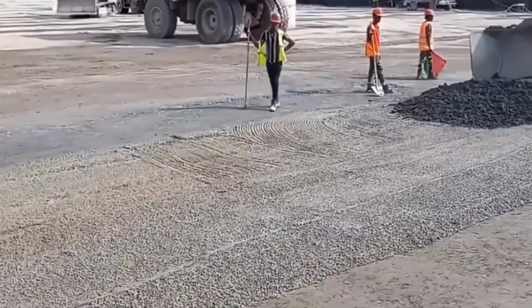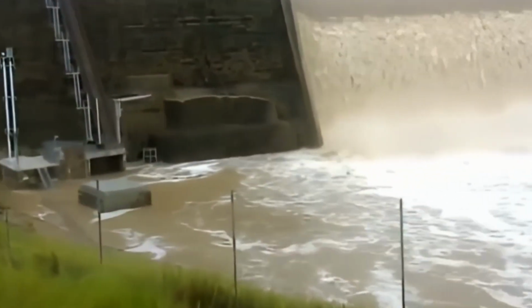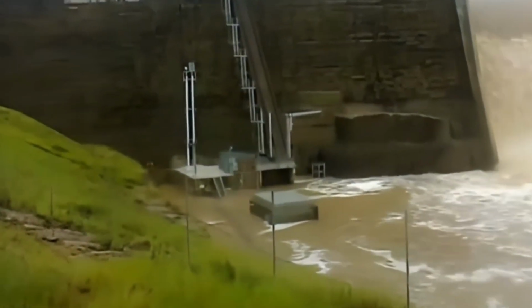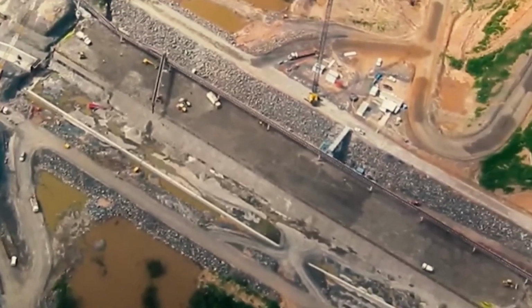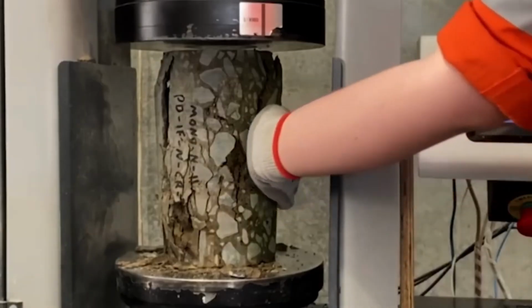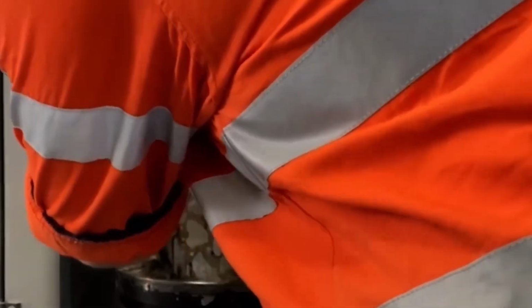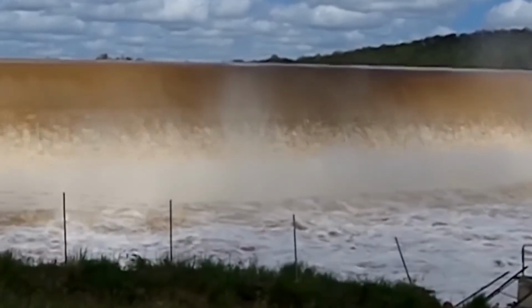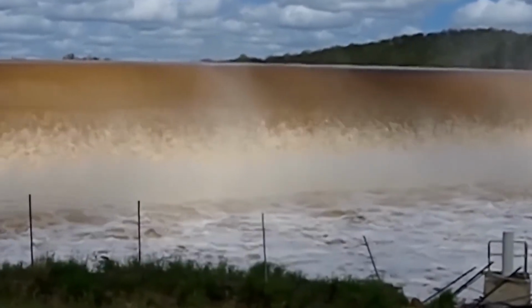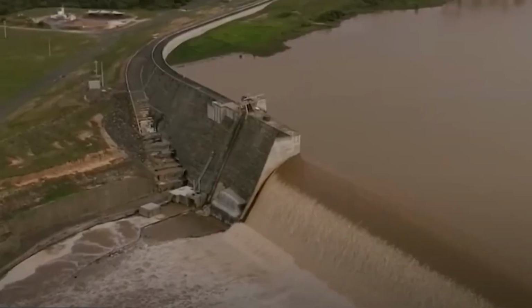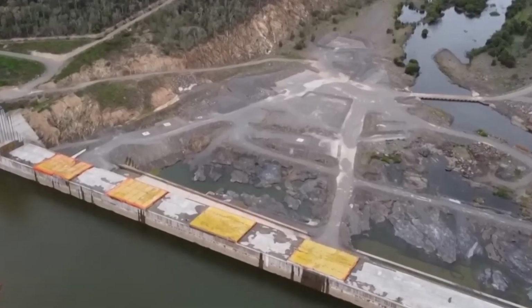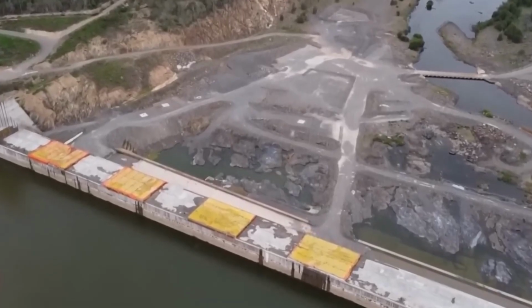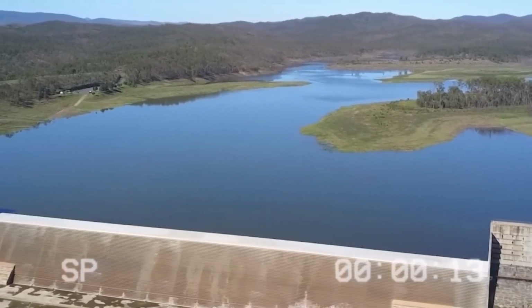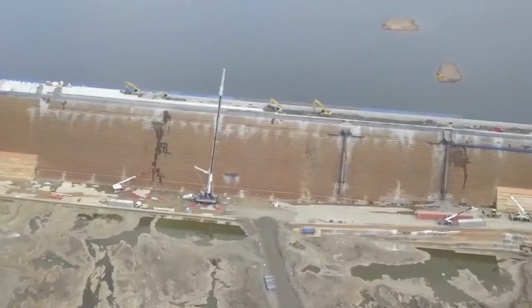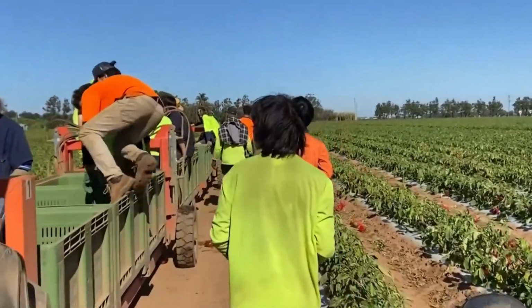First, the aggregate material, the crushed rock mixed into the concrete, was sourced locally from the riverbed. This basalt contained higher levels of clay than ideal and showed chemical reactivity that should have raised serious red flags. Second, the concrete mix itself was altered during construction. To cut costs, engineers reduced cement and fly ash content, producing an unusually lean mix. While this saved money up front, it also reduced long-term strength and durability. Crucially, this change was not subjected to adequate review or testing.